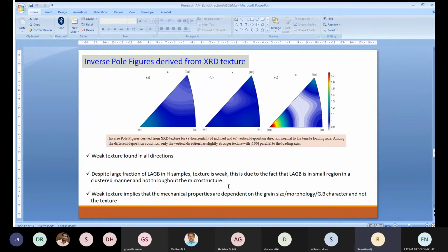So this weak texture is trying to tell us that the mechanical property is not depending on texture. It depends on the grain size and morphology and grain boundary character, not the texture.